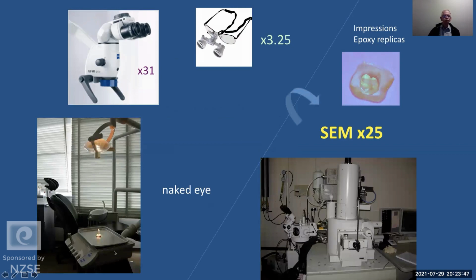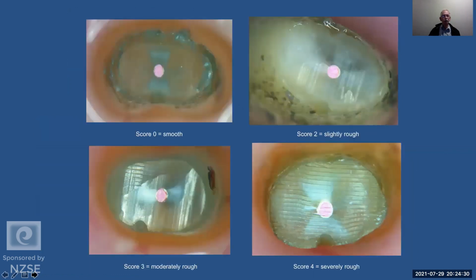Now, here's the experiment. Myself, Tina Howland, and Lara Friedlander all looked at these resections with our naked eyes. And then 2 weeks later, we looked at the teeth all over again in a random order with loupes. And then 2 weeks later, in another random order, we looked at them all with the microscope. And after each look, we took our little impressions and made epoxy replicas, and they went under the scanning electron microscope. So at no time did we damage and ruin the tooth so we couldn't take it to the next level. So there was an awful lot of looking at teeth and scoring their resected root faces.